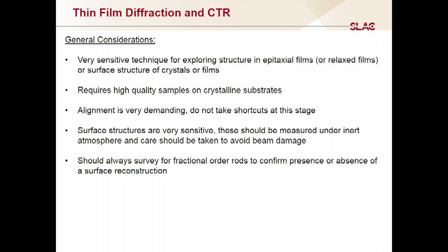And so some considerations then for thin film diffraction and CTR specifically: it's very sensitive for looking at epitaxial thin films or surface structure of crystals. You need really high quality samples on a crystalline substrate because the entire system needs to be essentially single crystal.